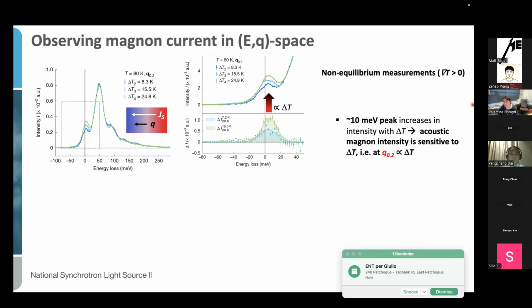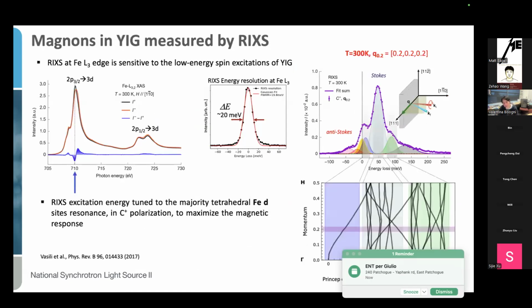Thanks. This is very interesting. So this was all dealing with acoustic magnons, right? Looking ahead, do you have any thoughts about optical magnons and that energy regime? It would have been nice to find out that optical magnons were having a significant role in this transport process, but the reality is pointing to not much going on at that high energy. In particular, because yttrium iron garnet has a very special optical magnon mode with a parabolic dispersion, one would have questioned if this strongly dispersing magnon mode was contributing, but experimental evidence suggests that not much is going on at higher energy in terms of involvement in the magnon process.